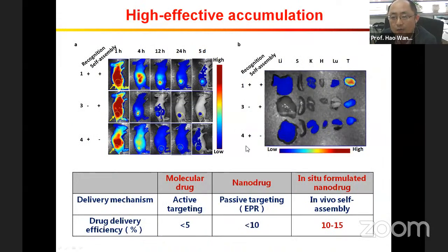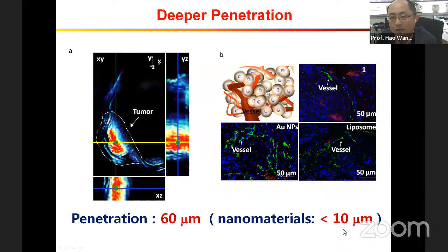And also in the mice study, we observed very good accumulation in the tumor. You can see this over 5 days. The top line is our positive molecule. Even at 5 days, you can still see a very good signal at the tumor site. But for the other control molecules, they just degraded or were cleared from the body. In our case, the delivery efficiency is 10 to 15% based on the mice model after 48 hours. Another advantage of this system is deeper tumor penetration compared to bigger nanoparticles.